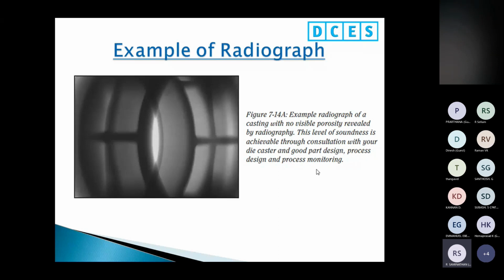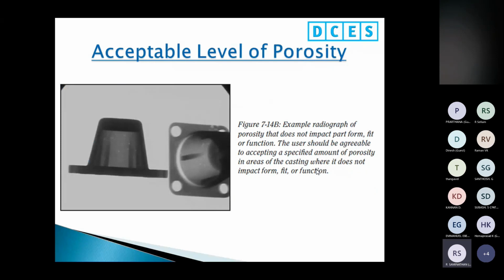This level of soundness is achievable through consultation with your diecaster and good part design, process design and process monitoring. This is an acceptable level of porosity. There is a small porosity, but it is acceptable. Example radiograph of porosity that does not impact form, fit and function. The user should be agreeable to accepting a specified amount of porosity in areas of the casting where it does not impact form, fit and function.